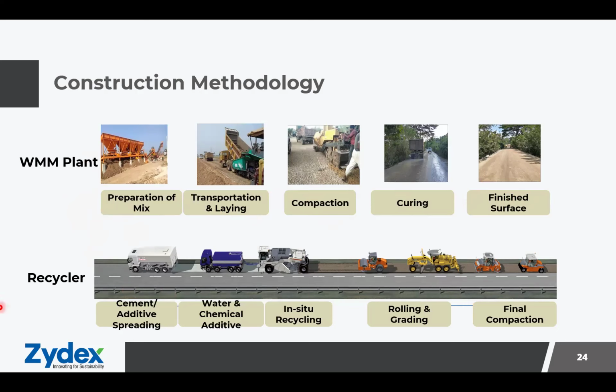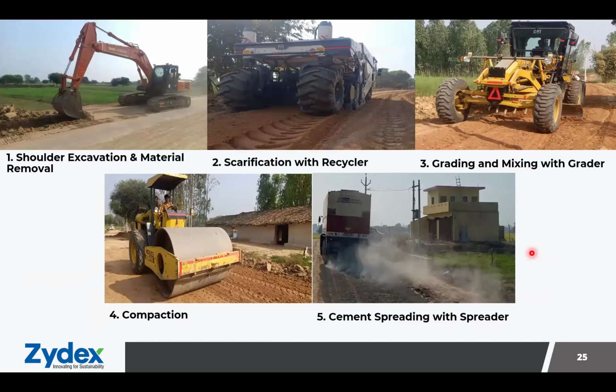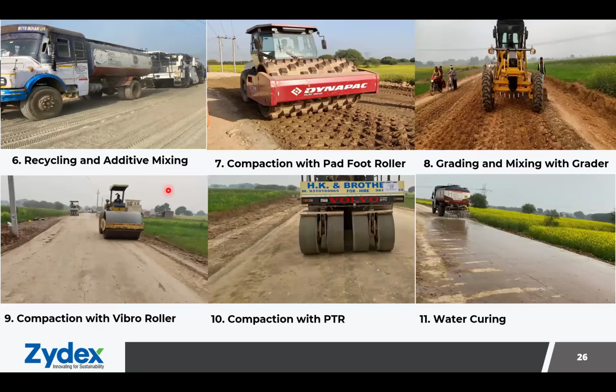Similarly, we can do this in a much more proper way by using a recycler. This includes cement or additive spreading as the first layer, then water and chemical additives addition, and then in situ recycling of the pavement layers. Further, it consists of rolling and grading as per the camber requirements, and then the final compaction using PTR and vibratory rollers. These are the first few photographs from the UP full depth reclamation that we have done, just a repetition of what I said in the last slide.